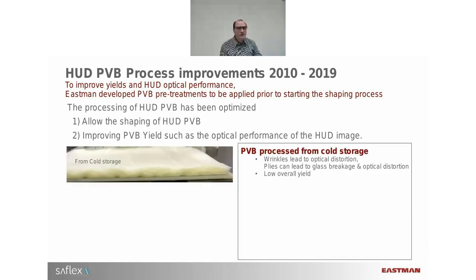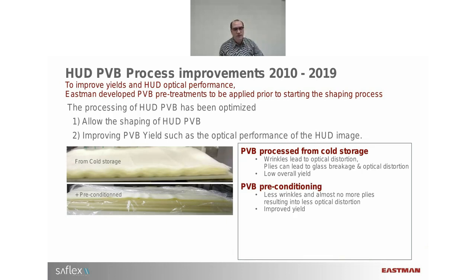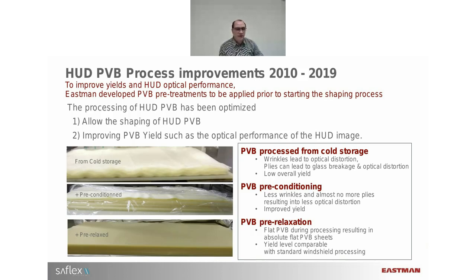Here you can see an example of a PVB, let's say without taking any precautions. When you take the PVB out of the cold room and you start processing, this is a typical ply which you get, where you can clearly notice the waves. If you precondition the PVB, you still can see waves, but it's already much, much better. And if you precondition and pre-relax the PVB, you obtain a flat PVB. If you have a single ply of PVB, it's very hard to see the difference with a traditional PVB, an acoustic or a non-acoustic. And you can compare the yield level with standard production.